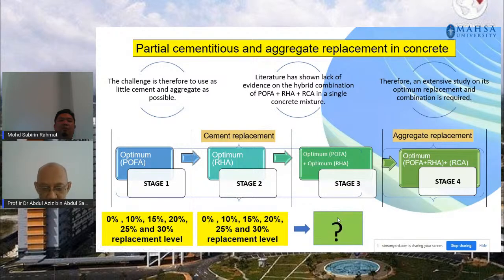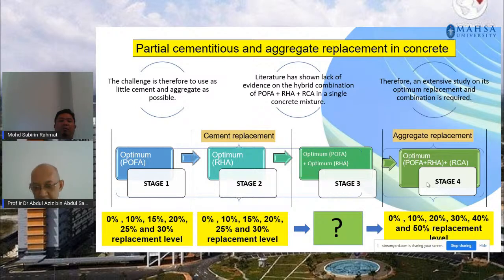Now in this study, I will show you later what percentages are acceptable to obtain a certain amount of strength that we have set for this green concrete. After achieving this mix of optimum percentages of the waste materials, I will go to stage 4, where I will combine all three waste materials, the optimum POFA and RHA, plus a percentage of aggregate replacement. The percentage of aggregate replacement I will be using is about 10% up to 50% replacement of RCA